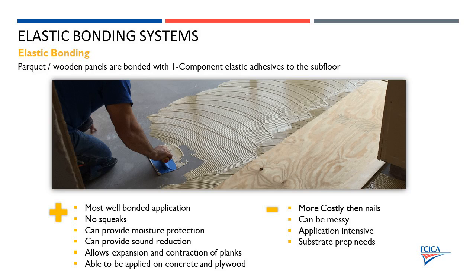The elastic bonding system. This has become the most popular system out there, really, to bond hardwood flooring or to install hardwood flooring. It's the most well-bonded application because you do get full spread on the adhesives. You don't have any squeaking because there's no nails in the system. So that's something important to stress to the end user or the homeowner. If you have concerns about having a squeaky hardwood floor, the adhesives remove the nails, remove the source of that squeaking 100%.